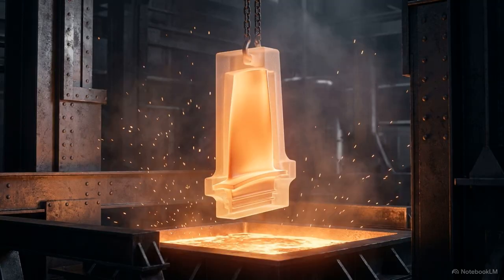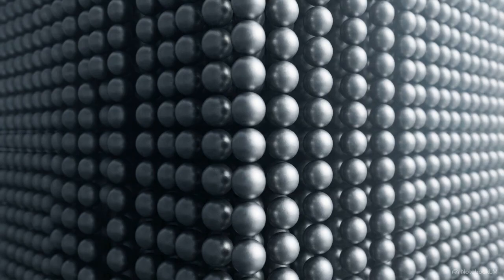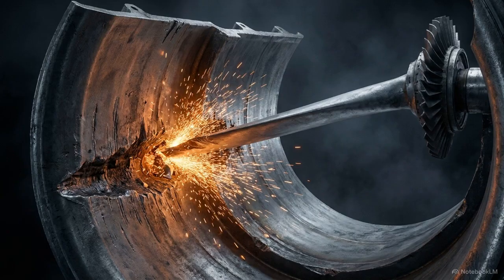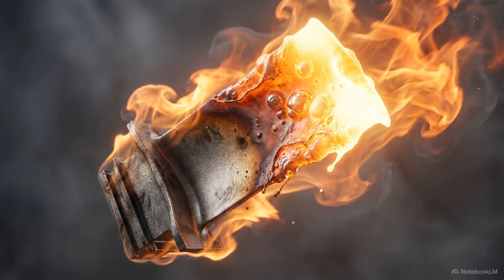To combat this, engineers use a highly controlled manufacturing process to cast each turbine blade as one continuous single crystal. By eliminating grain boundaries entirely, the single crystal blade achieves extreme resistance to creep deformation. Without this integrity, the centrifugal force would cause the blade to elongate until it smashed into the engine casing. Single crystal casting solves the mechanical problem of stretching, but a piece of nickel will still melt if exposed directly to a 1500-degree gas stream.